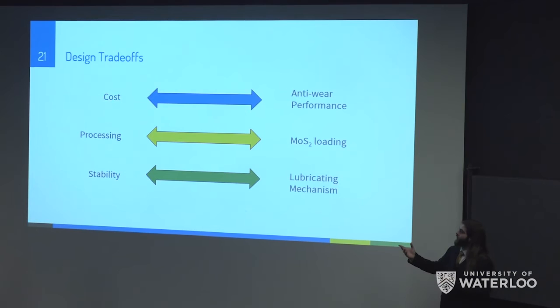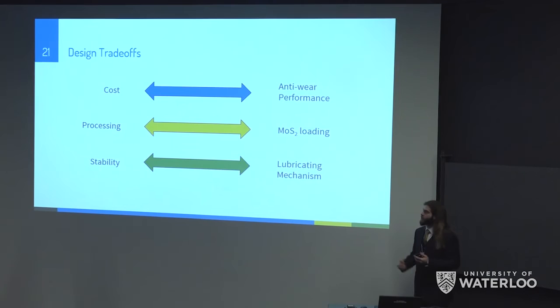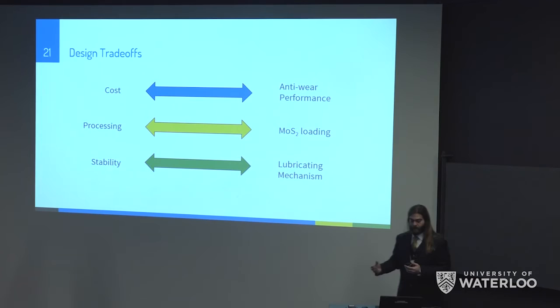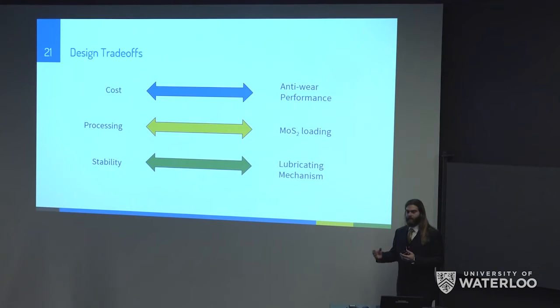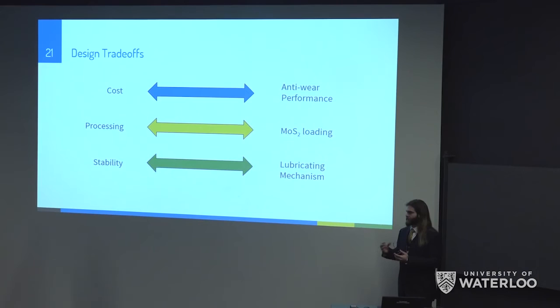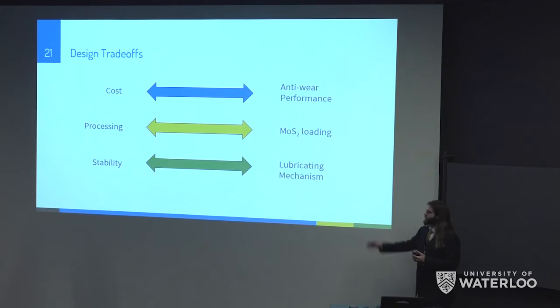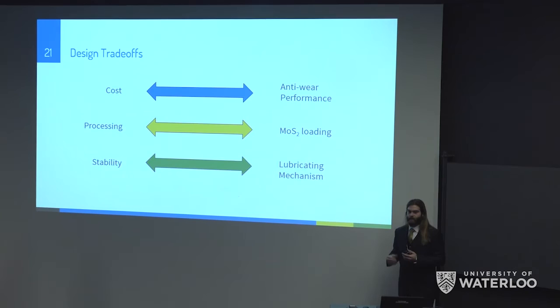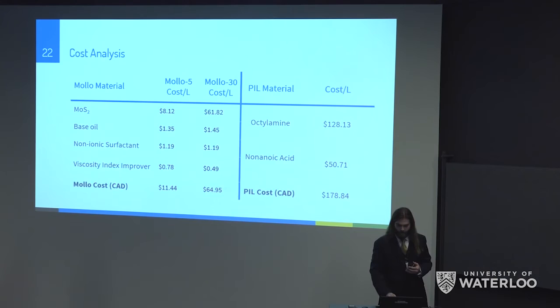Some key design trade-offs were identified. First, between cost and anti-wear performance: increasing MoS₂ loading improves anti-wear performance but becomes more expensive. Second, between processing difficulty and MoS₂ loading: higher MoS₂ content makes the solution thicker and more viscous, making it harder to synthesize and process. Third, between stability and lubrication mechanism: if the surfactant binds too tightly to the MoS₂ particles, the lubricating mechanism of MoS₂ is diminished, so a balance between stabilization and lubrication effectiveness must be maintained.